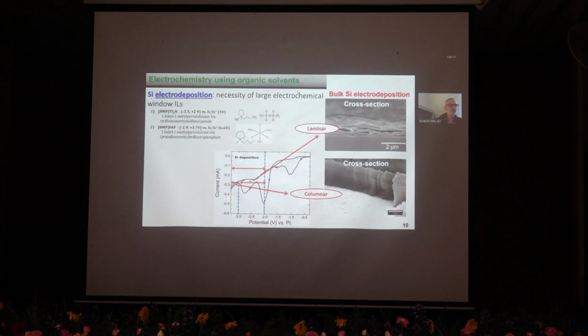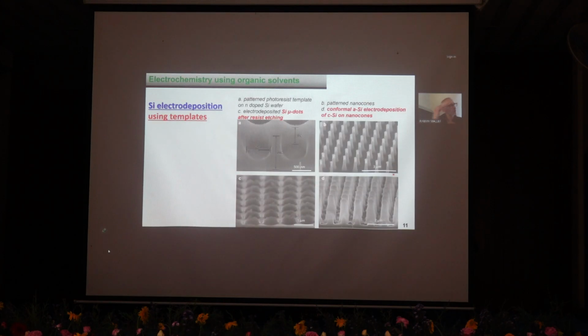On the right side, we have some bulk silicon electrodeposition. We have two SEM images showing that by adjusting the synthesis parameters, potential, current, temperature, it is possible to control the morphology. So here we have, for instance, the possibility of having some laminar growth or columnar growth of the silicon just by adjusting the parameters.